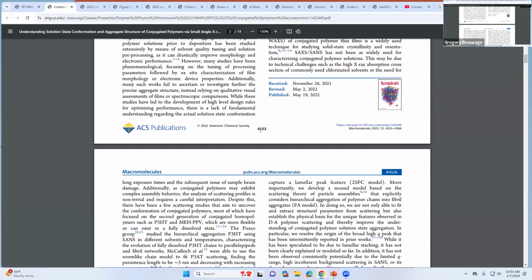So yeah, how do we come into the branches? Well, like this GPC machine, you can get the molecular weight. So you can have different detectors on the end. One, so it's coming out in time, it's separating the molecular weight, and it's a dilute solution. So it's coming out in a little tube, and you can shoot a beam of light in, do light scattering, and get the radius of gyration and also the weight average molecular weight from light scattering. Then you can do a refractive index detector and calibrate it with some other polymer that you put through. So just how much stuff is there or not, yes or no. So it gives you a signal of that.